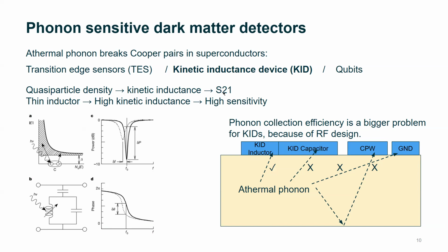We call that the S21 signal. You see the signal both in the amplitude and in the phase. We call the amplitude the dissipative signal, and the phase signal. So same idea here, because what matters is the quasi-particle density, naturally you want a smaller inductor in the resonator, a physically smaller inductor. You want it thinner in thickness and thinner in width, so it gives you higher quasi-particle density and a higher sensitivity.